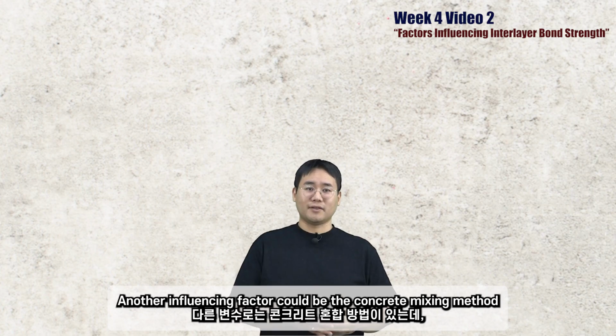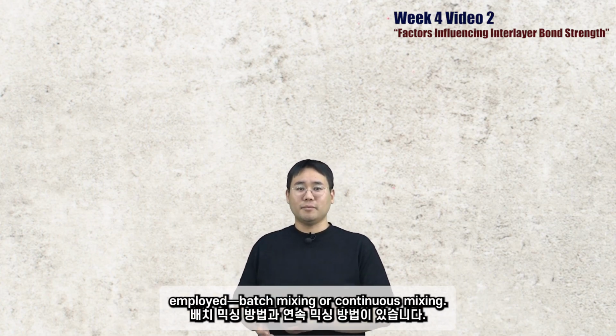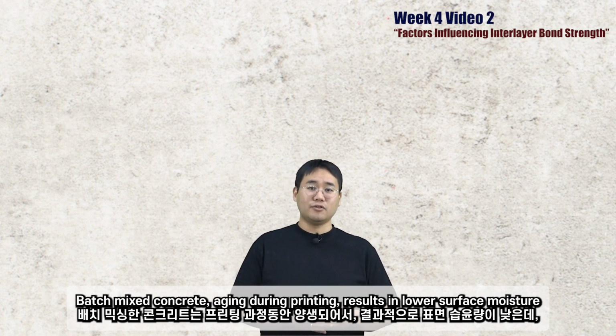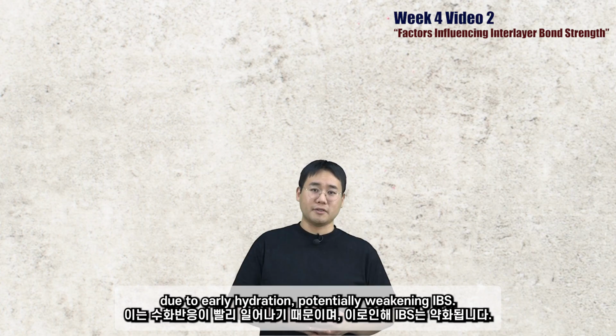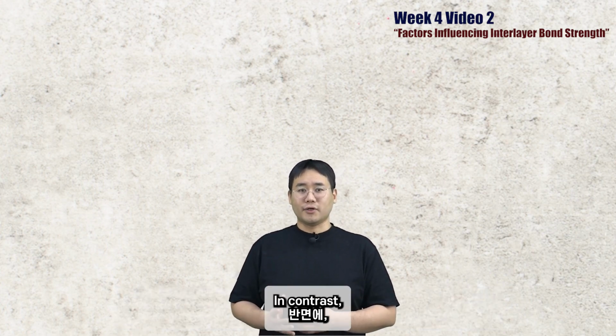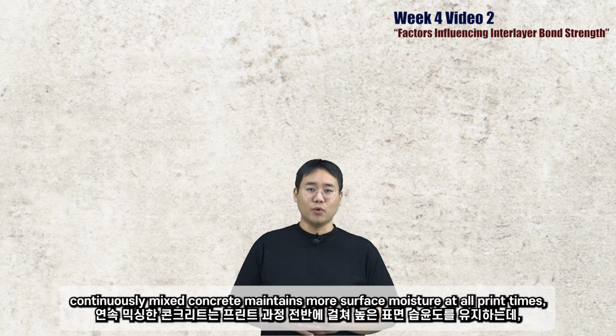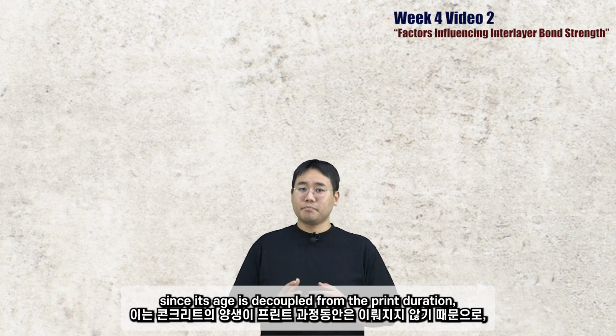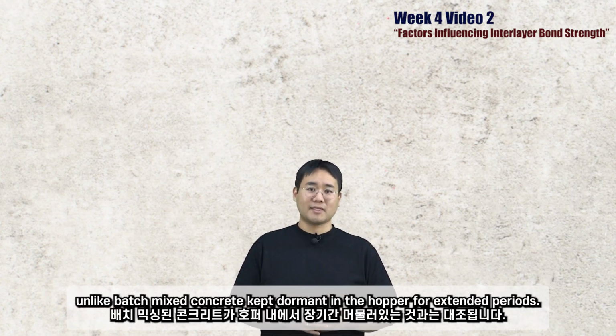Another influencing factor could be the concrete mixing method employed, batch mixing or continuous mixing. Batch mixed concrete aging during printing results in lower surface moisture due to early hydration, potentially weakening IBS. In contrast, continuous mixed concrete maintains more surface moisture at all times since its age is decoupled from the print duration, unlike batch mixed concrete kept dormant in the hopper for extended periods.